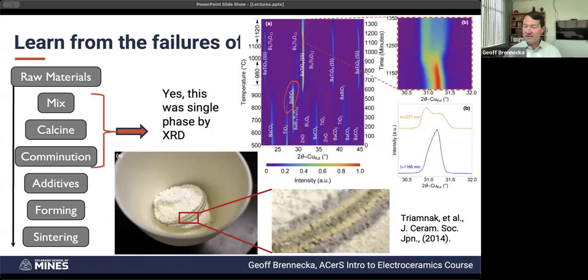But these complex reactions where we're just taking two perovskites and mixing them together and heating them up, it's never that simple because atoms have to diffuse and they can only go so far, and they're going to happily react with whatever's nearby rather than whatever reaction that you threw down on a piece of paper. And so you can end up with a lot more complexity along the way than you ever expected. And maybe you give it enough time that you end up getting somewhere near equilibrium and all is well. But maybe you don't, and you don't necessarily know the kinetics of the process going into it.